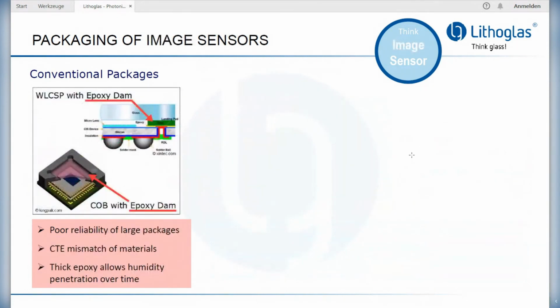And image sensors is more of a niche market. As you may know, most is done in either wafer-level chip size packaging, where a glass lid is attached with an epoxy dam to the silicon sensor on wafer level, and then after adding the contact, it's cut into pieces. Or if it's a chip-on-board package, a piece of glass is glued into the package with a thick epoxy dam. This works sufficiently well for most applications, but the larger the image sensor gets and the larger the package needs to get, the CTE mismatch of the materials turns out to be a bigger problem, because the epoxy will just expand much stronger on temperature change, and so reliability is an issue.